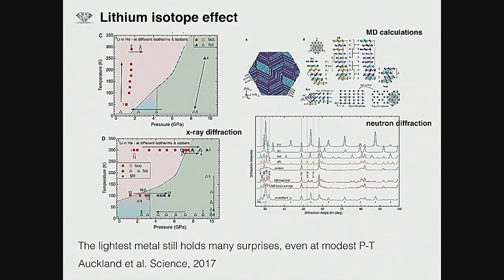Another very recent, very impressive result is about lithium. So again, an element, the lightest of metals, is as simple as it can get. We should know everything about elements, you think. And this group shows so many impressive results already at very low pressures. You see these plots end at roughly 10 GPa. These are pressures that the high pressure community has been able to reach for a very long time. Of course, this is low temperature as well.